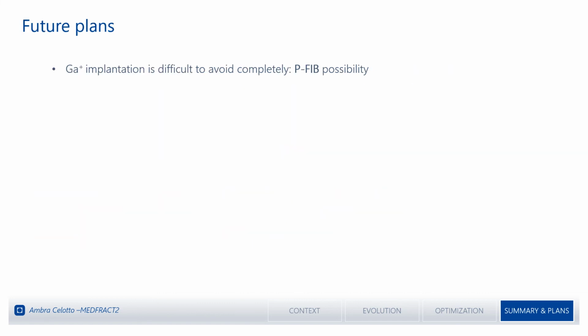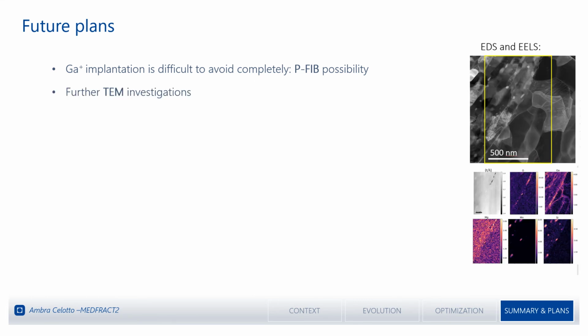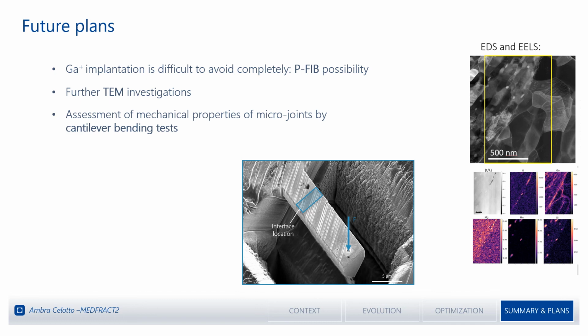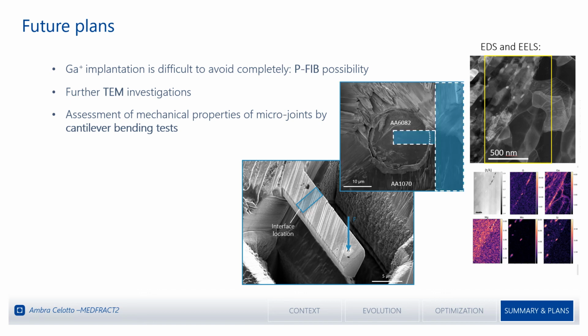So future plans. For solving this issue of the gallium implantation, we are considering the employment of a plasma FIB, which exploits argon ions instead of gallium ions. Then people from the group are working to investigate the bonding mechanisms at the nanoscale by transmission electron microscopy with the TEM. And we are working on creating some cantilevers out of the microjoint in this location here to perform bending tests by nanoindentation of those.